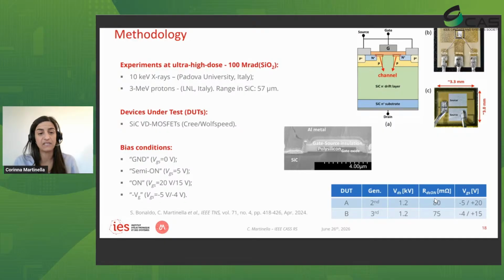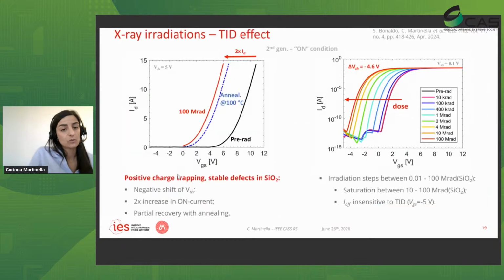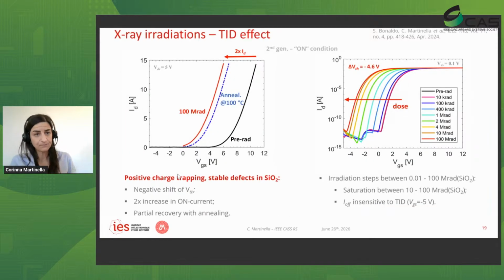We can test them in ground conditions, so we have 0 at the gate, or in on condition when we apply the maximum bias that is possible to apply at the gate, semi-on when we apply an intermediate bias between ground and on, or off condition when we apply the maximum negative bias that is allowed by the manufacturer. I'll start by showing you the results from the X-ray irradiation.